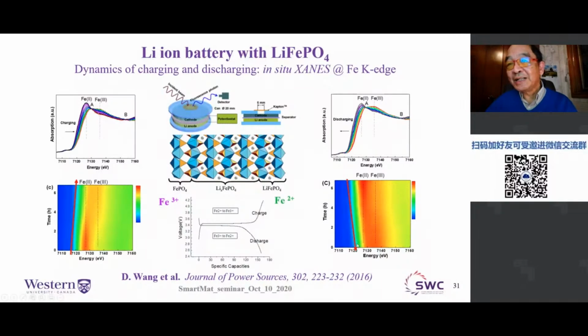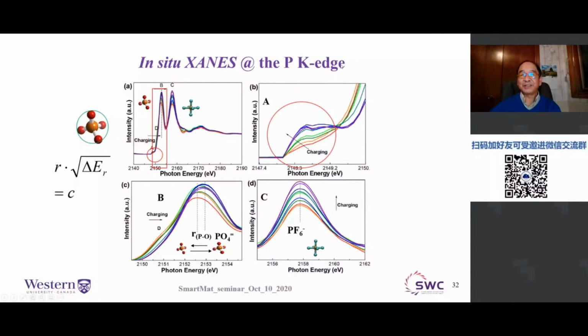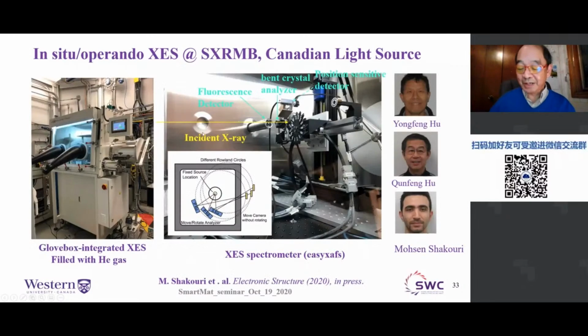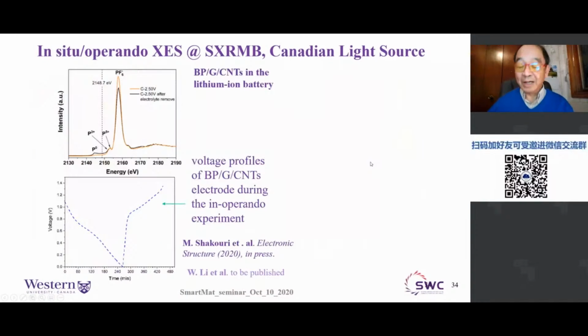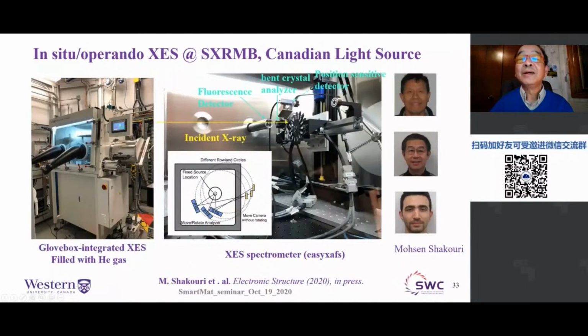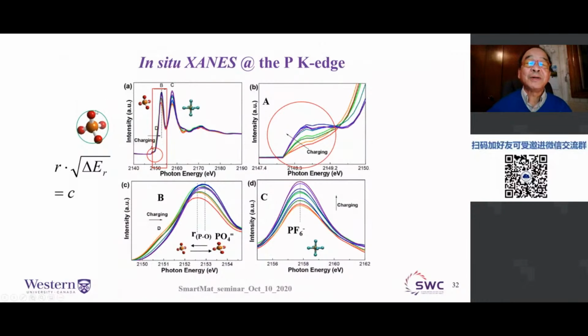Okay, now, and you can see the direction is reversible. And we can also see the phosphorus, right? With the phosphorus, we not only can see the iron, how it changes, we can see phosphorus changes. Of course, there's no chemical change of phosphorus. But when lithium ion goes in and out, it distorts the tetrahedral structure, becomes normal.